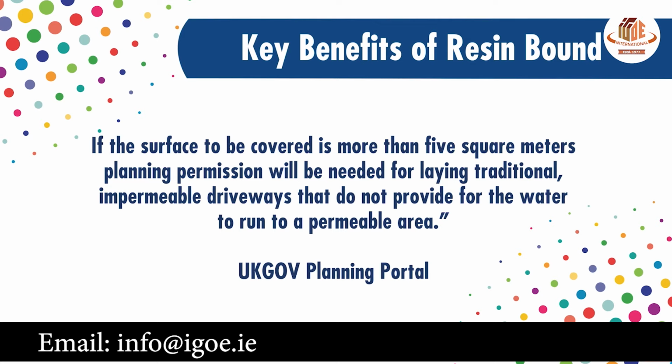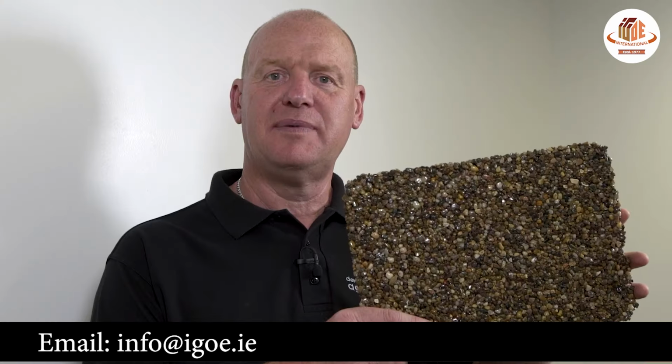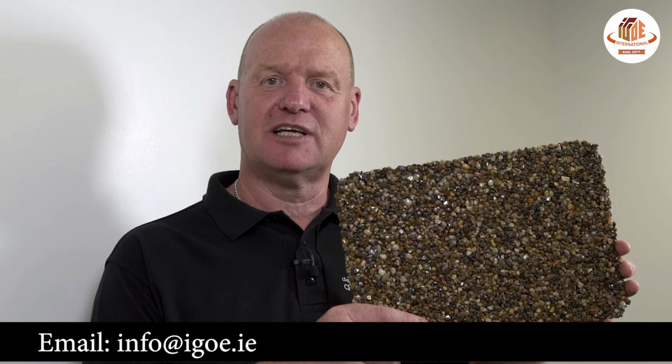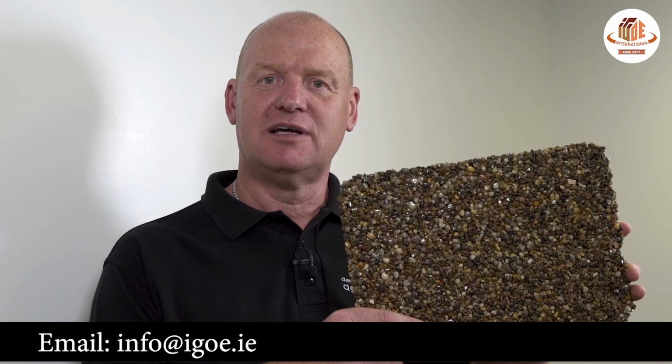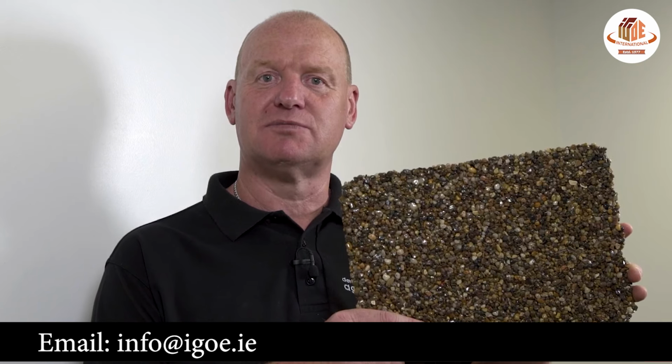Let's look at just how permeable it is. The permeability of resin-bound is 850 litres per square metre per minute. It's never going to rain that hard. Here's a simple way to show your customers the permeability.